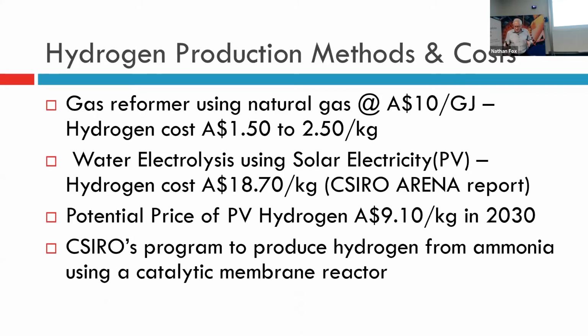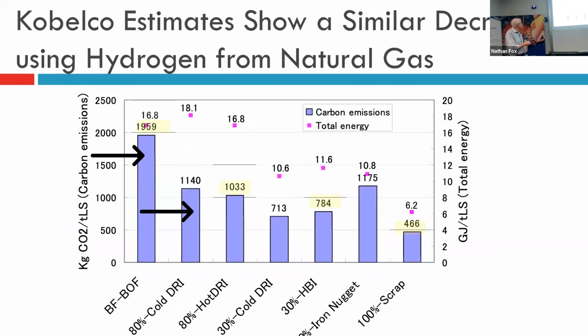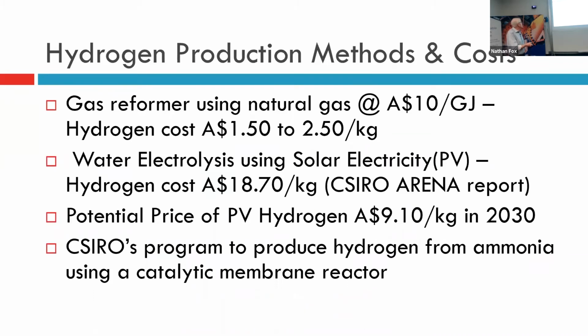If you use natural gas, and currently it's about $8 to $10 a gigajoule, hydrogen costs about $1.50 to $2 a kilogram to produce. If you use water electrolysis, the CSIRO ARENA report is indicating about $19 a kilo. So it's confirmed my calculation, about 10 times the cost. The CSIRO are saying that they may be able to get the price down to about half that, about $9 a kilo by 2030 with techniques that they're looking at. And there are some good techniques that they're looking at now for electrolyzing. There are catalytic reactions that they're looking at that could make it quite competitive.